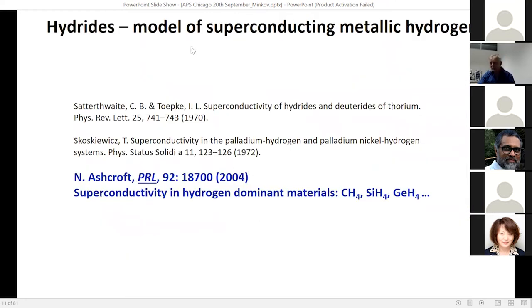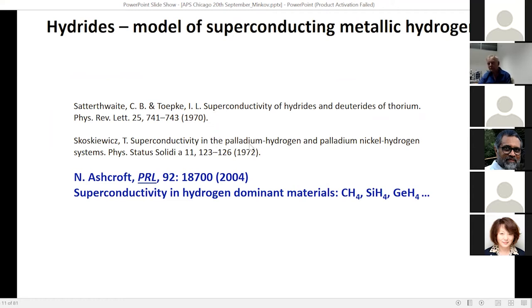To reach superconducting hydrogen we still need very high pressures — around five megabars. So people long searched for how to substitute metallic hydrogen with hydrides. For instance, hydrogen goes easily inside palladium in an atomic state, but this turned out to be a very poor model for metallic hydrogen.